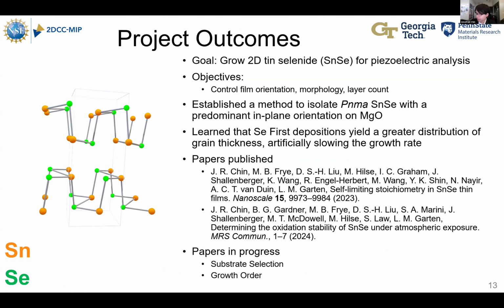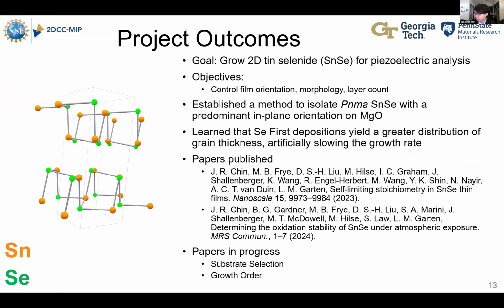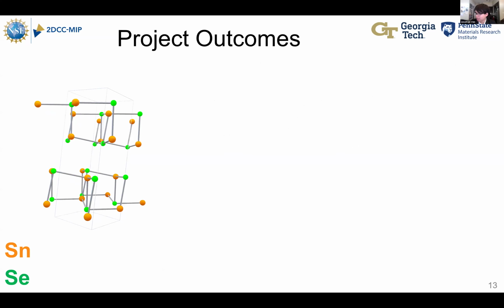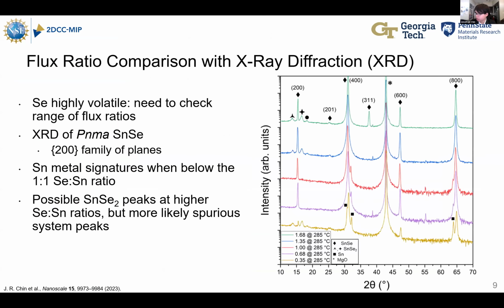So in our XRD, we can see that we do have predominant out-of-plane in the 200. So this is focusing on tin selenide on MgO, where we can see the out-of-plane with 200, 400 orientation. So that's where we're going for, this kind of middle, around this 1.35 flux ratio. Once the flux ratio increases too far, we start getting these 201, 311 orientations.